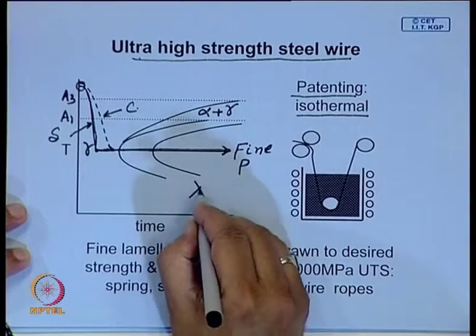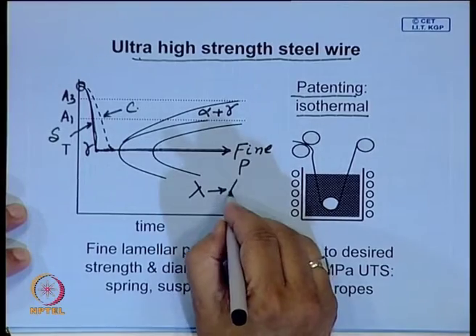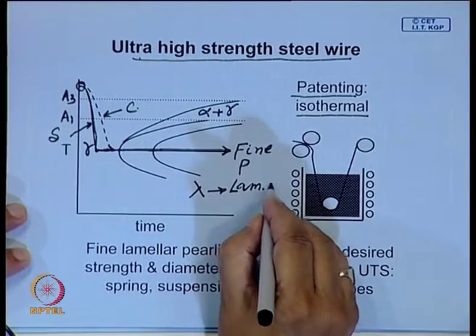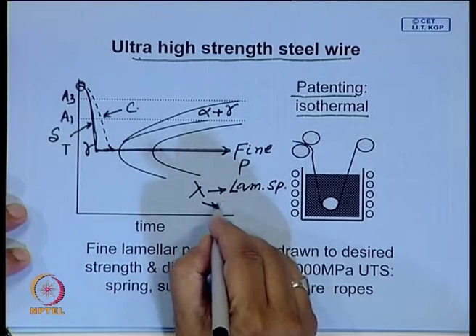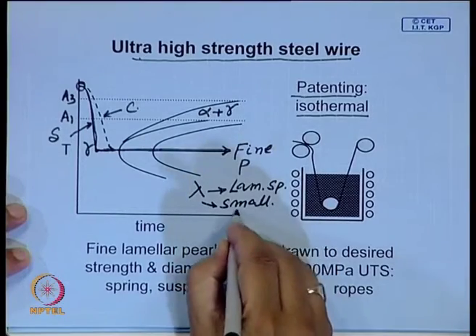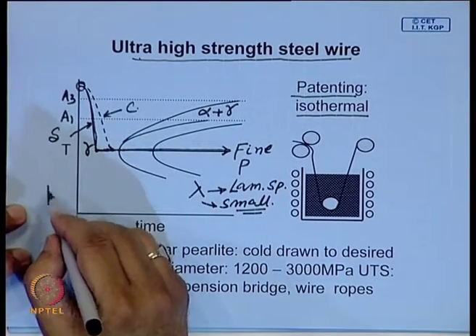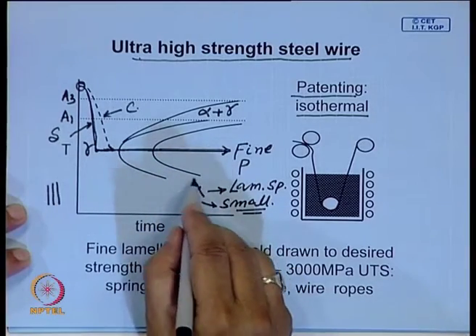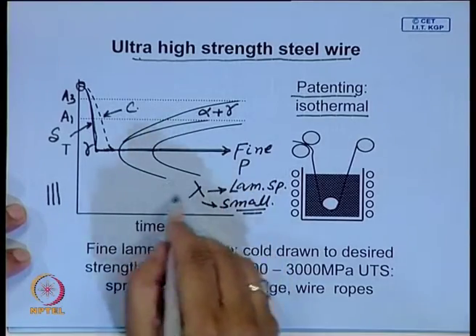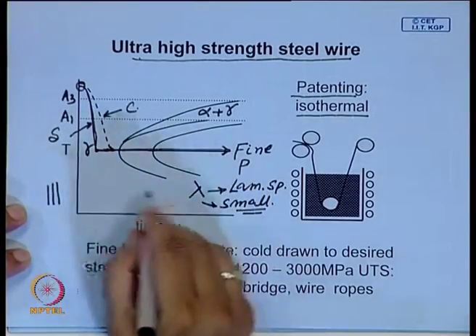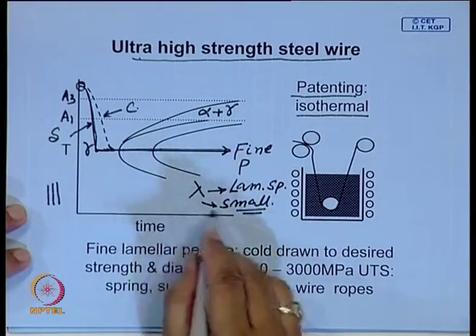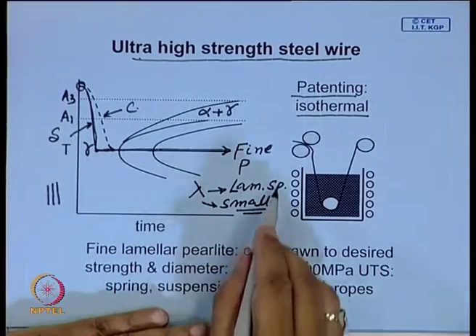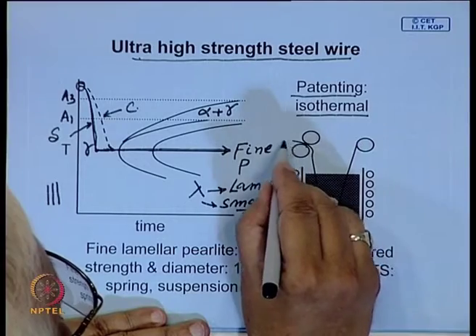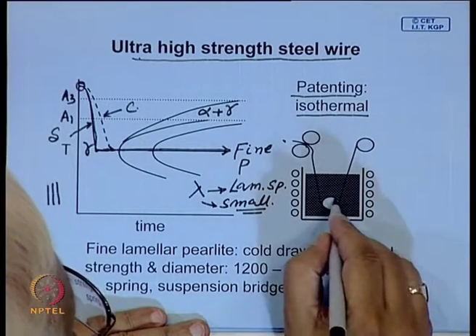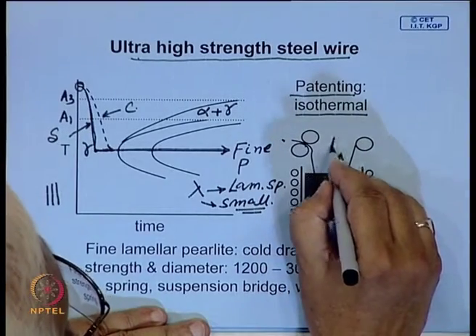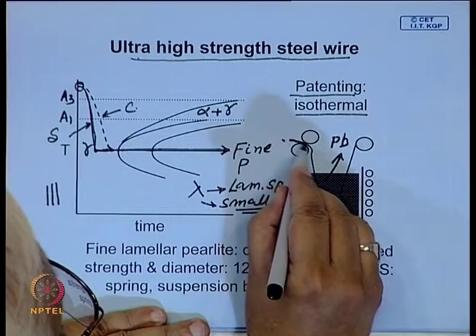That means the lamellar spacing lambda is really small, and under an optical microscope the pearlite will not resolve. In normal pearlite you do see these kinds of lamellar structure, but the main idea is that in a standard optical microscope you will find that most of these pearlite nodules are not resolvable. And how is it done? The wire passes through these guide rolls, and this is an ideal guide. This is a lead bath, molten lead, and the wire passes through here.